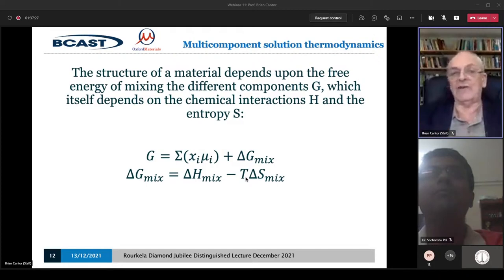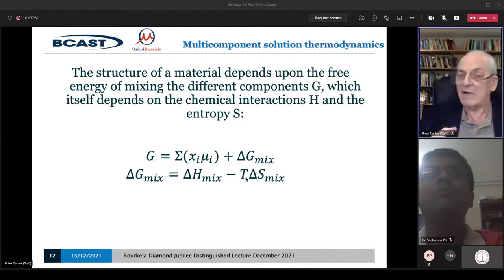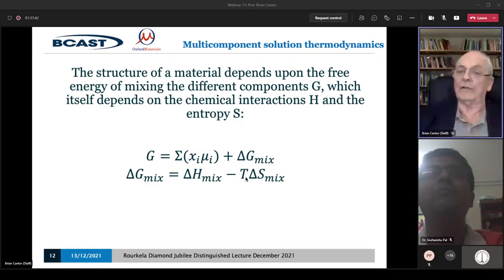It depends what you want. If you want a material that's stable over that period, running at 800 degrees for 3 years, then there's going to be a problem with the Cantor alloy. But there will be other alloys that will be more stable than that. Just like most steels are more stable than that, there will be other multi-component alloys which will be more stable than that. And we have to do the studies to find them.